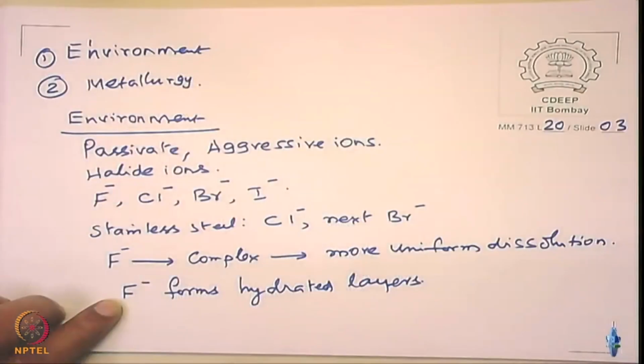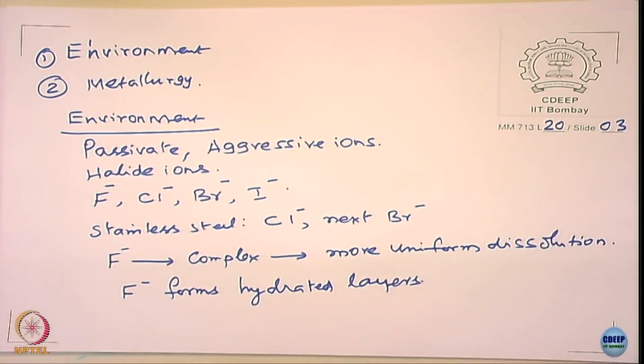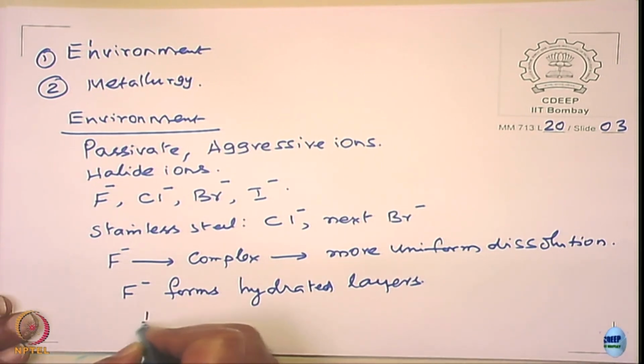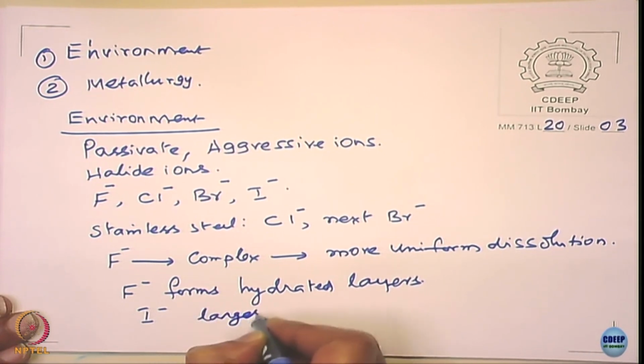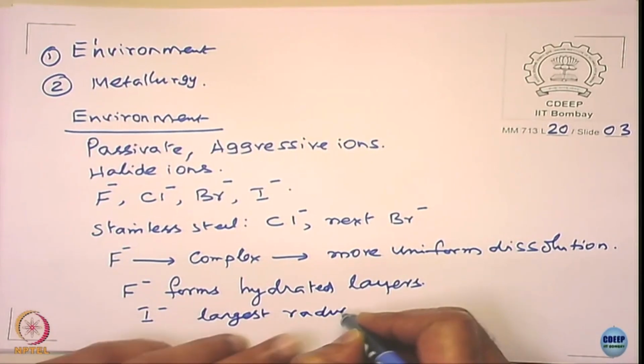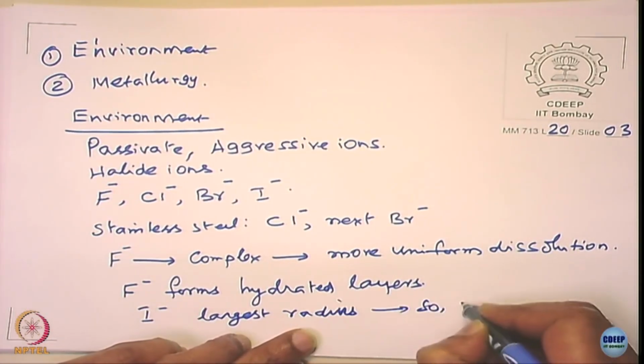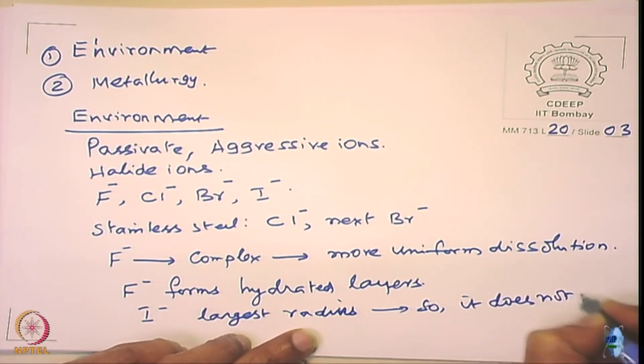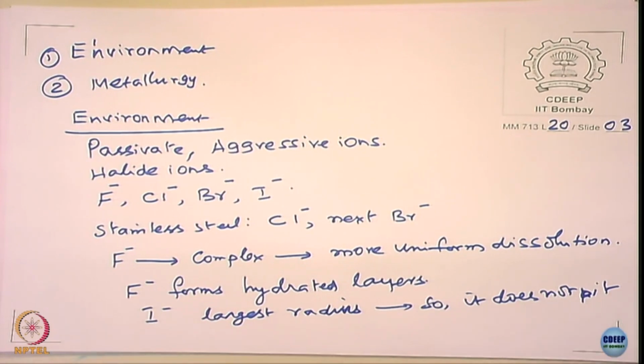So when you have a fluoride, it is getting hydrated, it's very strongly hydrated, then you do not allow the water to come out and free the fluoride ions, because to remove the water molecules from the fluoride ions is more difficult because the charge density is more on fluoride as compared to the chloride. So the two reasons make the fluorides less aggressive towards pitting as compared to the chlorides. And iodide is the largest radius. So it does not pit. Does not cause pitting rather actually, okay.